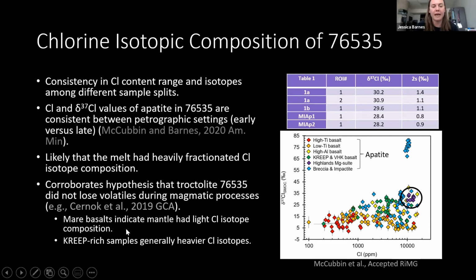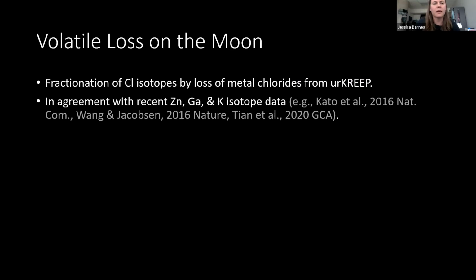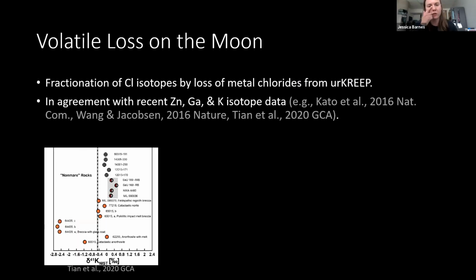Okay, and so what we conclude again is that mare basalts indicate the mantle had a light chlorine isotope composition, whereas any KREEP-rich samples like this Apollo 17 troctolite sample have heavier chlorine isotope composition. And so what we're saying is that fractionation of chlorine isotopes was likely caused by the loss of metal chlorides from urKREEP shortly after the lunar magma ocean had finished crystallizing. And this is in agreement with other moderately volatile elements. Some recent work has looked at zinc isotopes, gallium isotopes, and also potassium isotopes, and show very similar patterns to what we're seeing.